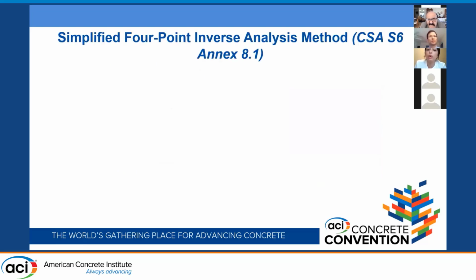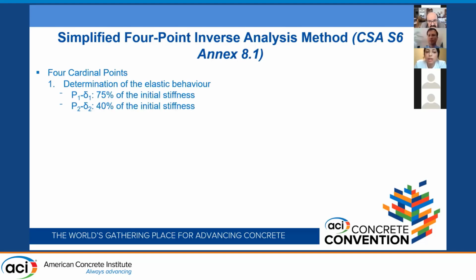Now, what about the method I'm talking about? It's a simplified 4-point inverse analysis, which is a simplified method, but at the same time, it ensures accuracy. This method is based on extracting 4 cardinal points from the experimental load deflection curve. The first 2 points are from the elastic behavior, and they correspond to the intersection of the graph with 75% and 40% of the initial stiffness.